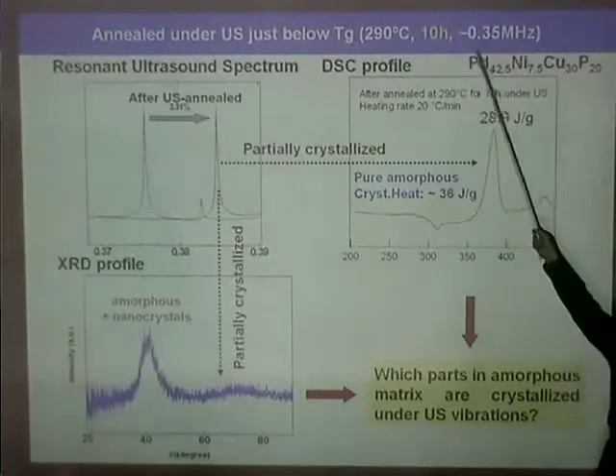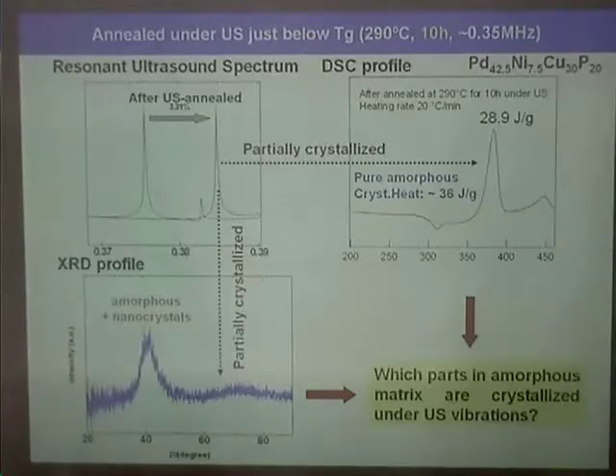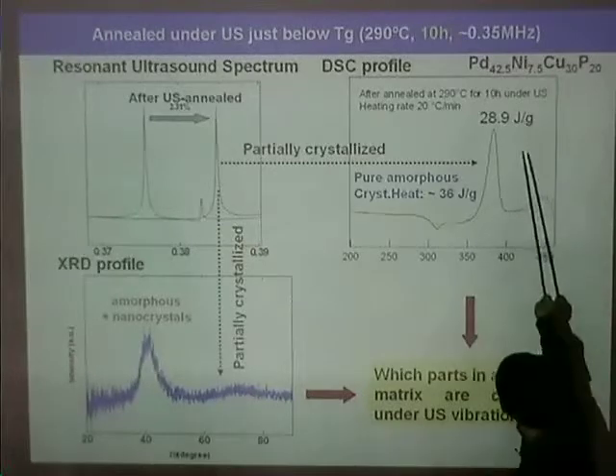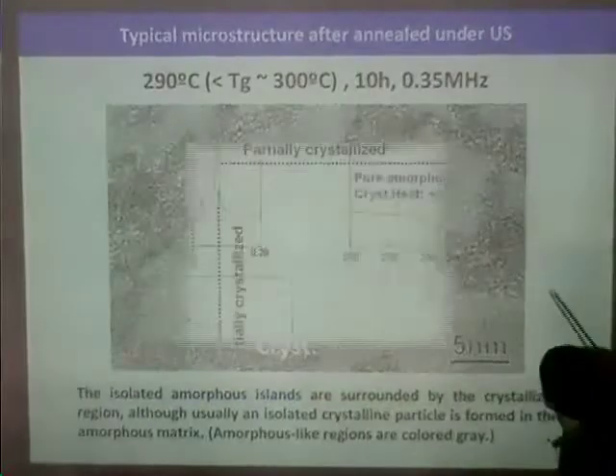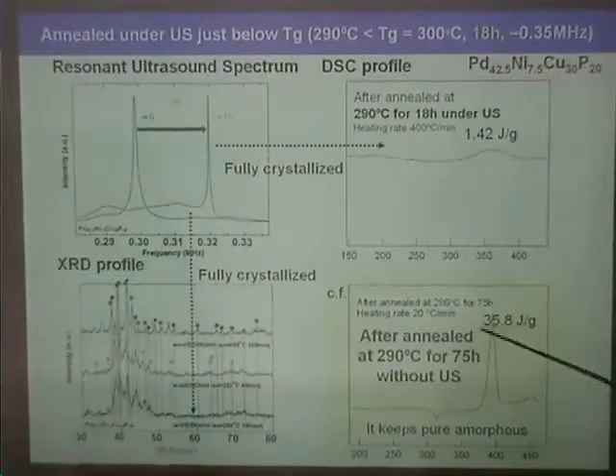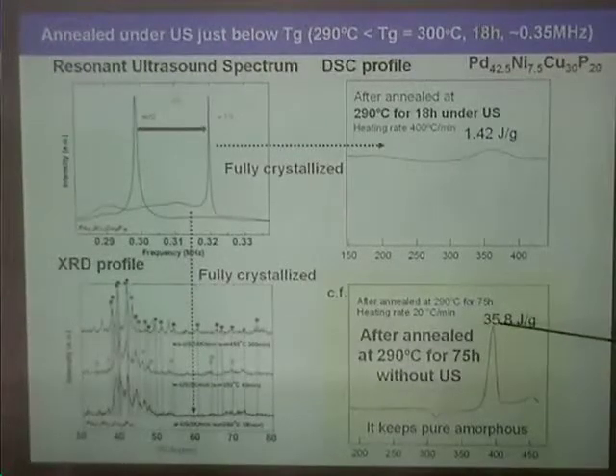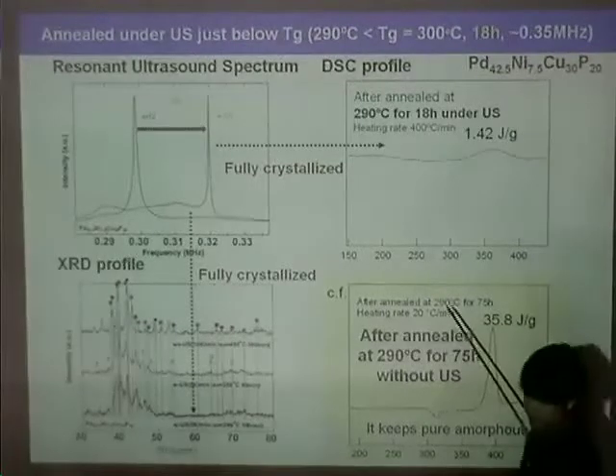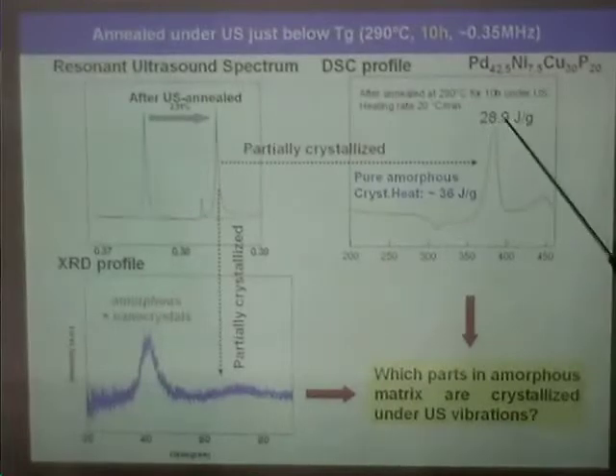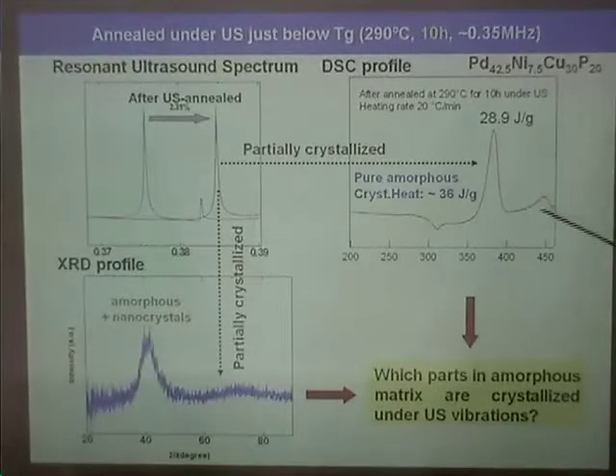In the case of only 10-hour annealing, what happens? We can imagine that partial crystallization occurs. DSC indicated that the crystallization heat is slightly decreased. The full crystallization heat is 36 joules per gram, but in this case 29. Therefore, partial crystallization occurs.